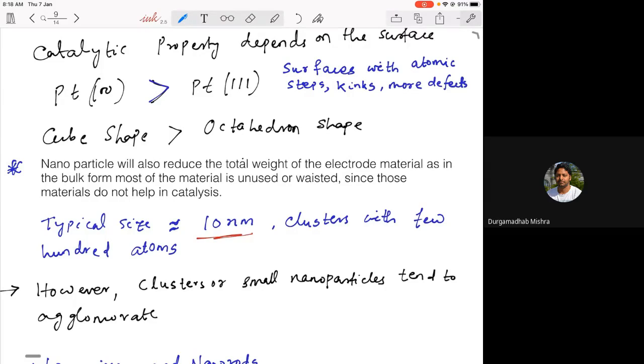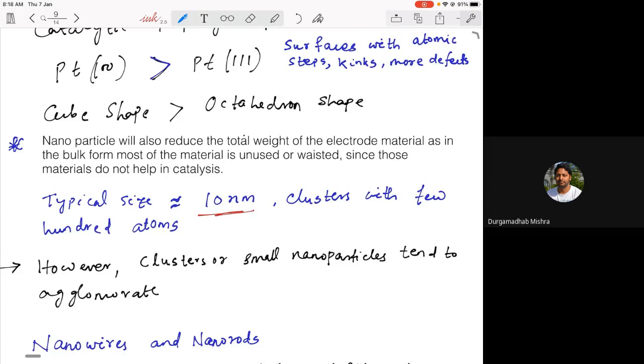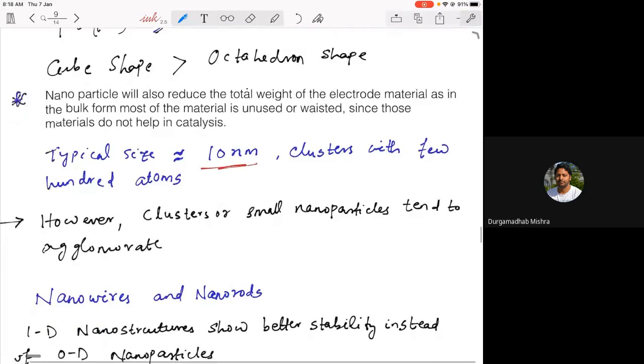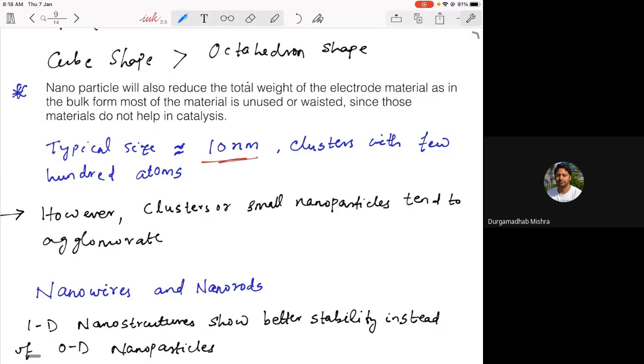But you cannot passivate the surface, because once you passivate, you also lose the catalytic property of the surface. That is actually a big bottleneck in platinum nanoparticles as well. This agglomeration can hamper the catalytic behavior of the electrode. And therefore, people thought of using wires and rods. So instead of nanoparticles, these nanowires or nanorods have extended surfaces.